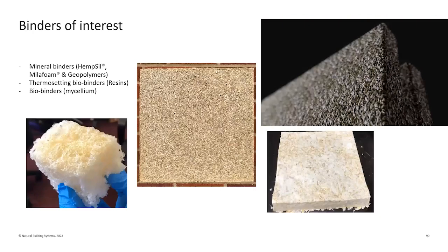It has a different pore structure, but nonetheless, it's got very good insulative properties. So we're sticking these together with different binders. We're using a range of different binders in this project. So the HempSil binder, a Milafoam binder, which is another mineral binder that I've developed, which is completely fireproof.